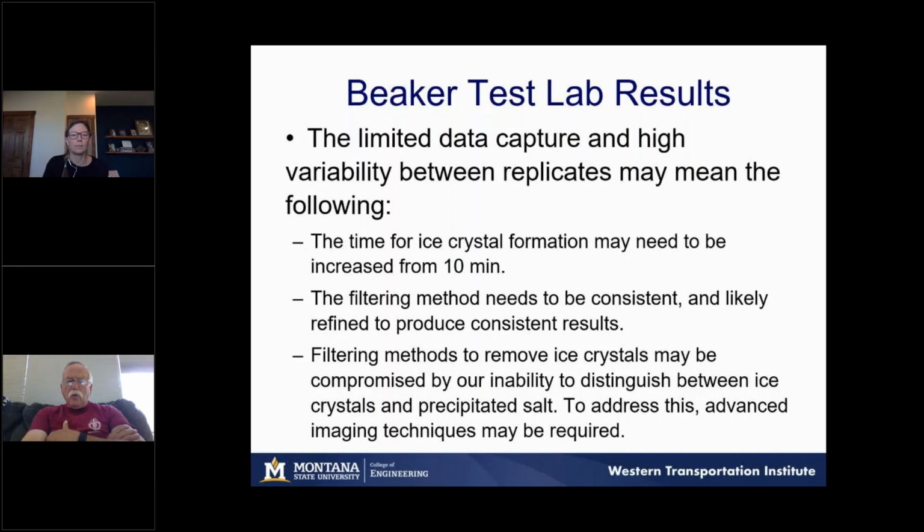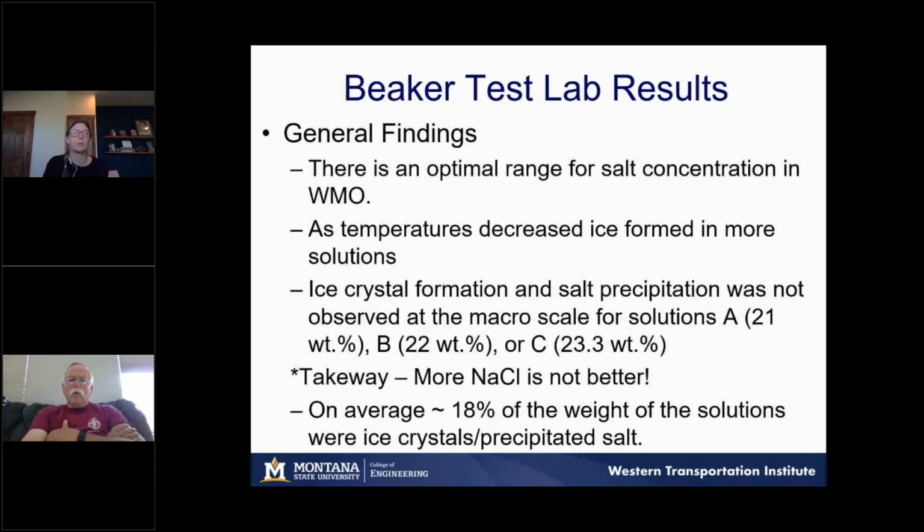But overall, again, we're very happy with the images and how those came out, and we feel like they do help paint a picture for what is hopefully seen in the field can now be shown image-wise in the lab. The general findings are that there is an optimal salt concentration range for winter maintenance operations, and that as temperatures decreased, ice formed in solutions. Ice crystal formation and salt precipitation was not observed in the lower concentration solutions, which is to be expected. So again, the takeaway is that more salt is not always better.